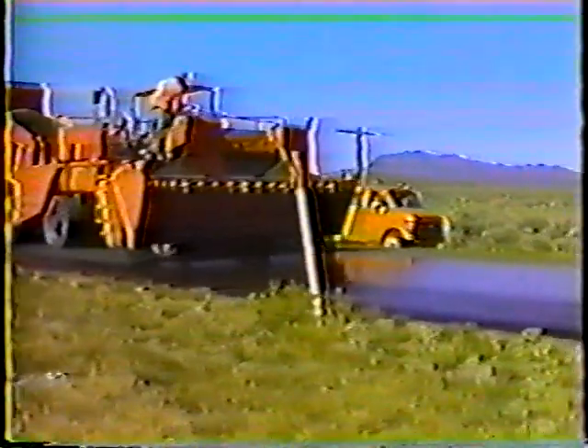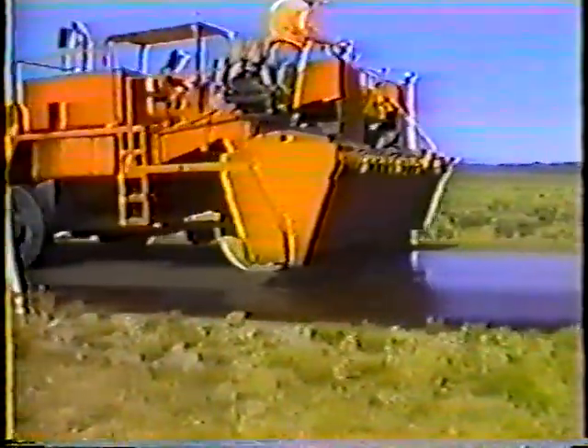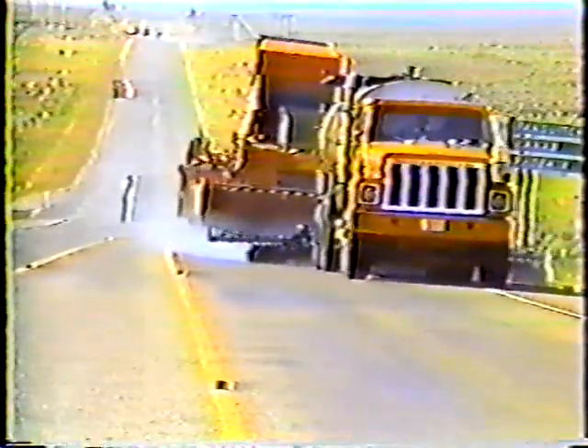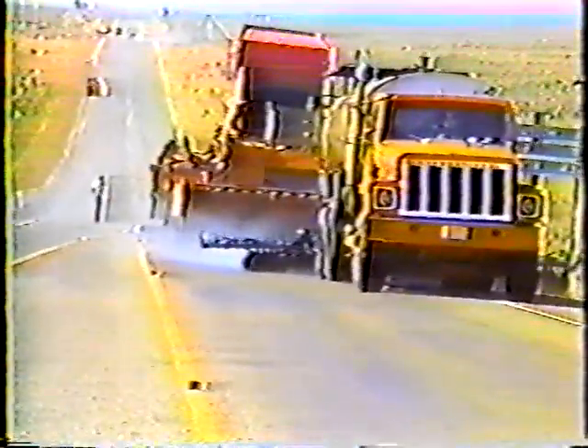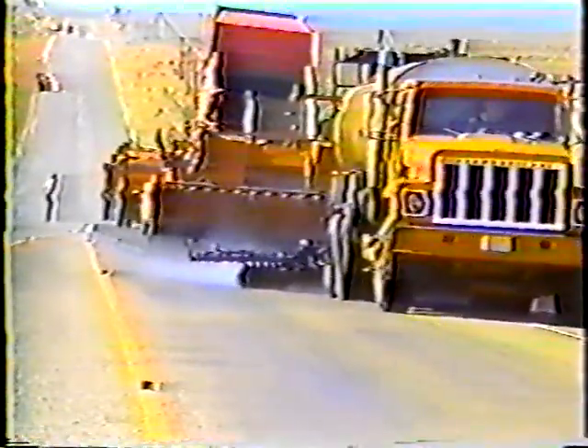As I said, it's important that the cover material be placed as soon as possible after the liquid asphalt has been applied. So the only solution is to hold the speed of the distributor to about 6 miles per hour. That way the material stays where it's put and the chip spreader stays close to the distributor. As I said, the chip spreader should not be more than 200 feet from the distributor, but the closer they stay together, the better.